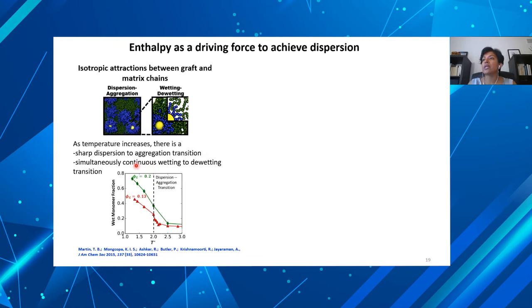Low temperatures, the matrix is happy to wet the grafted layer, mixing with the grafted layer. That's what the y-axis is telling you. And at high temperatures, the demixing of the graft and the matrix causes demixing of the particle and the matrix polymer, and leads to aggregation. The important thing that we found was that these two are not just identical transitions. Wetting to dewetting is continuous, while dispersion to aggregation was a first order transition. So that's just a little bit extra physics there.